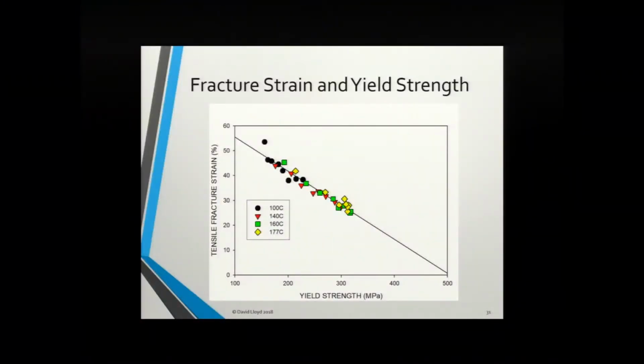This shows that fracture strain yield strength relationship for those aged alloys that I just showed, and you can see the scaling that you've got. So if you have, this is the yield strength, this is the tensile fracture strain, if you have that plot, you can merrily move around quite happily.